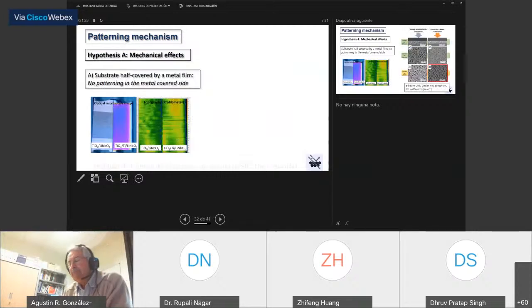However, this hypothesis is somehow contradicted by some experiments that we carried out. For example, if we perform a similar experiment on this single crystal lithium niobate covered partially with a very thin titanium film, which is a metal, we can see that in the uncovered area, the area which was not covered by titanium, we get the 2D pattern, while in the titanium covered area, we don't get any pattern.